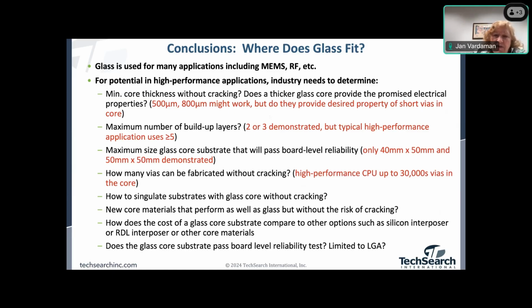The maximum size of the glass core substrate to pass board level reliability. We've seen a little bit on a 40 by 50 millimeter size and maybe a 50 by 50 millimeter, some of the work that Sony had done, but nothing past that. And that was just specifically to pass, it was an acceptable reliability for their application for an image sensor. But it's not clear that that same reliability test would meet the needs of the high performance applications. So that's yet to be determined.